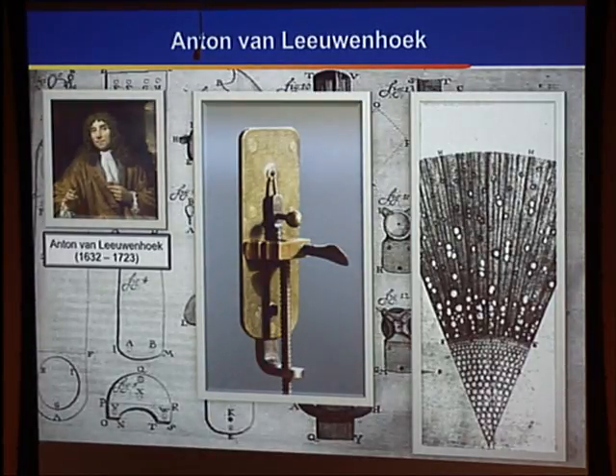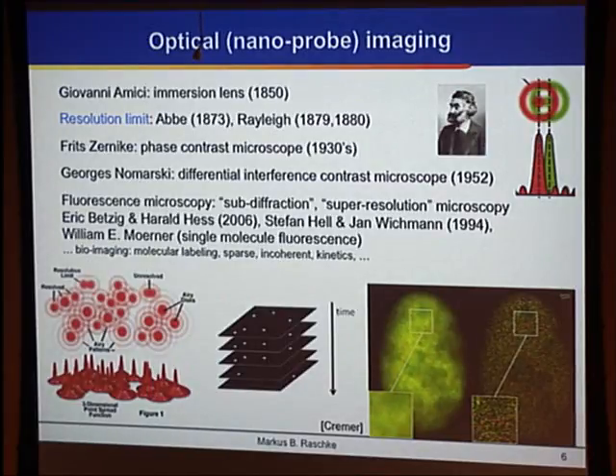Now, the evolution of optical microscopy took many routes, increasing in terms of spectral content, sensitivity, and so forth. And then most recently, as many of you know, it reached, even in the far field, past the notion of the diffraction limit, even though this is debatable nomenclature, where you reconstruct the point spread function center of gravity by taking advantage of fluorescent labels, which you can trigger to emit in a stochastic fashion, and then you can reconstruct an image also way below the diffraction limit.